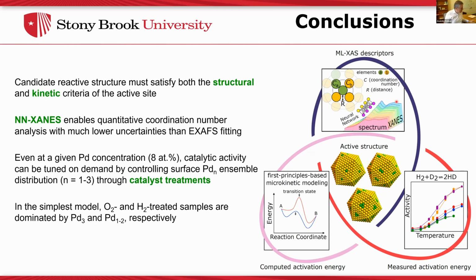So the conclusions of this, and I'll have time for questions, are that our reactive structures are obtained and they satisfy both structural and kinetic constraints. I didn't say anything about kinetic modeling to save time, but we've done microkinetic modeling of full reaction pathways using the DFT calculated barriers. And they all confirm the measured activities, which was a much more accurate way of modeling it than by using DFT alone, but that's in the paper. And so we can also say that neural network XANES is not just some kind of scientific curiosity, but it's really a useful tool to link structure and activity studies. And also it can measure coordination numbers quite accurately and with lower uncertainties than by XAFS.